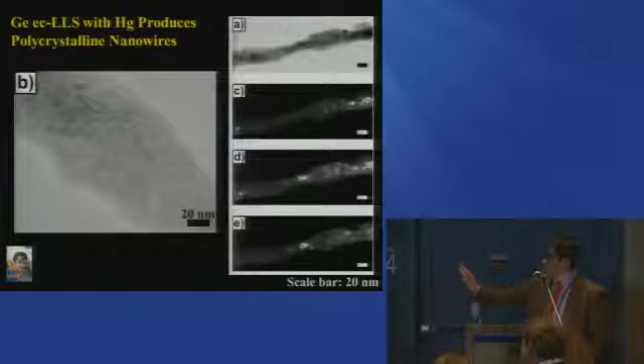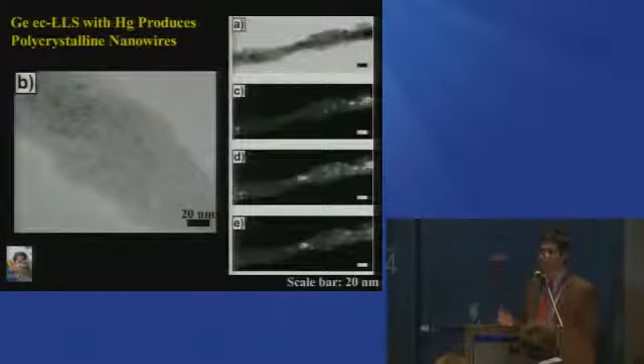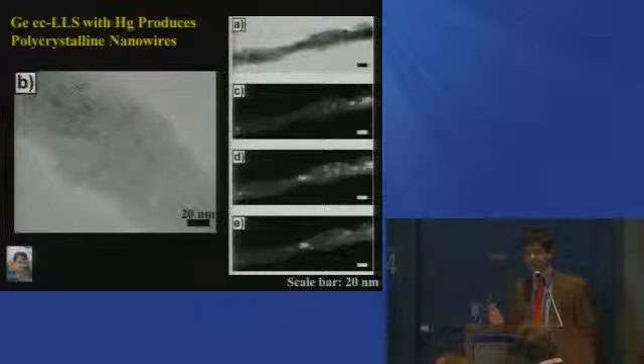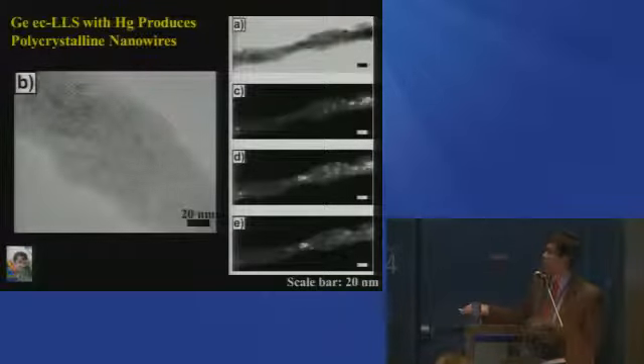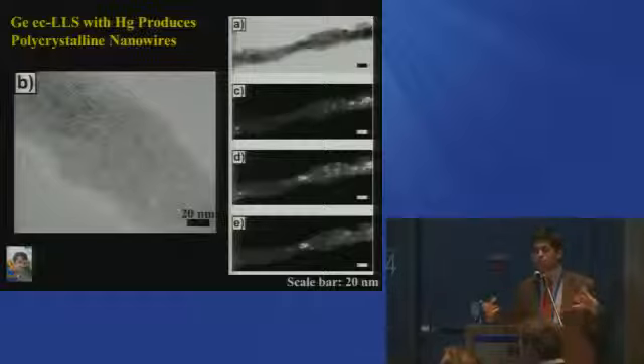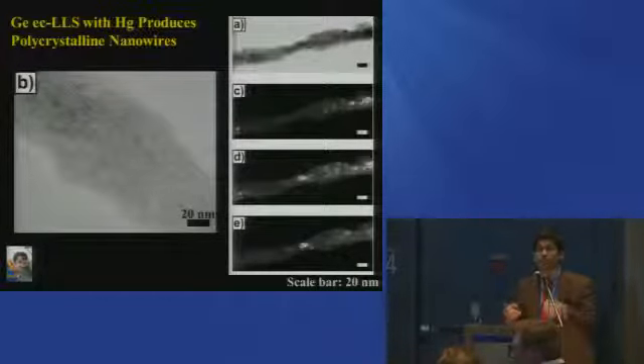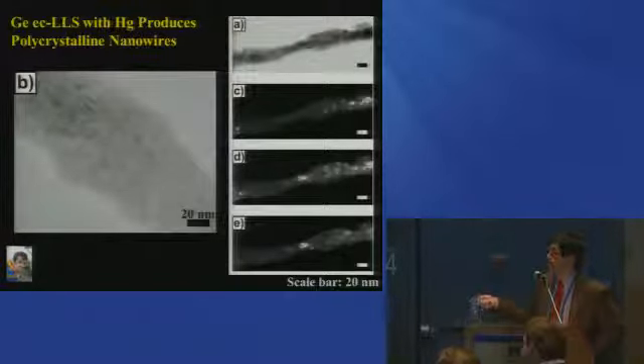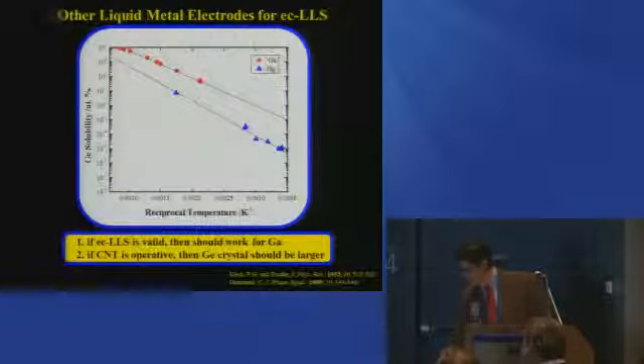This initial batch of nanowires that we were making with mercury, and just to be clear, they were crystalline, they were very pure, but they were not high quality in the highest sense. They were polycrystalline. If you took a high-res electron micrograph of any one of these germanium nanowires, they were all composed of grains of crystalline germanium, but they were more or less randomly fused, which indicates that what you were doing is crystallizing germanium very fast in a relatively small volume. But this is not equivalent to a really high-grade material.